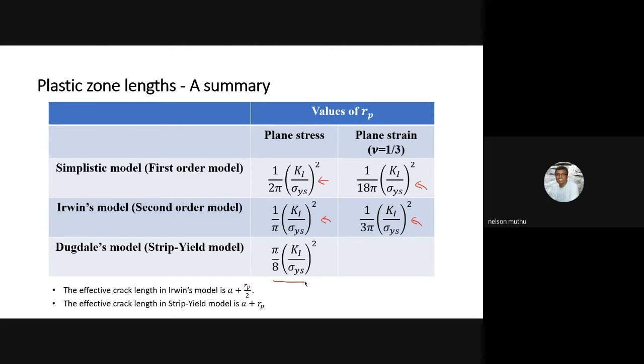The second difference is the effective crack length. You see, in the case of Irwin's model, the effective crack length is A plus RP by 2, or A plus lambda. Whereas in the case of the strip yield model, the effective crack length is A plus RP. There's a difference. Or it is approximately equal to A plus 2 lambda. Now you can ask why this apparent difference. As I said to you, these are all models. In order to make use of the LEFM principles with ease, in spite of plasticity, such models have been introduced.